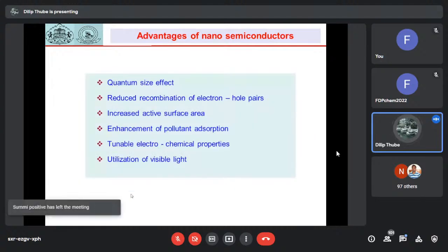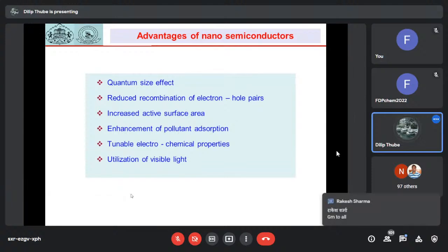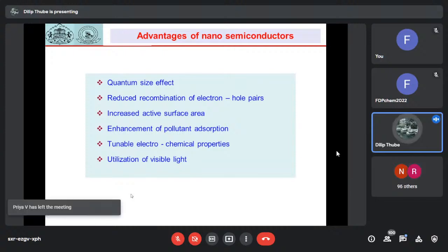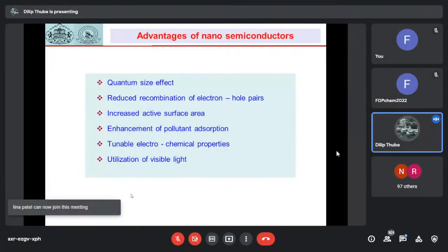And therefore, instead of making use of bulk semiconductor materials, nano semiconductor materials can be used because of the quantum size effect. They have reduced electron hole recombination rate. They have increased surface area, because of which adsorption properties increased, and therefore large number of pollutant molecules are adsorbed on the surface of the catalyst, as well as due to the modification of the material, electrochemical properties can be tuned, and therefore materials can be used for the visible light adsorption.